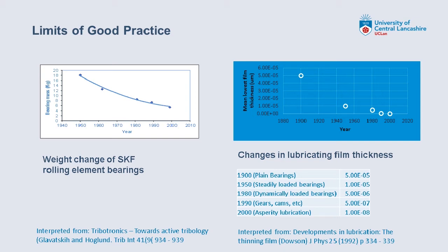If we look at the curve on the right, this curve illustrates typical operating film thicknesses since 1900. And you can see here that in 1900, operating film thicknesses were of the order of 50 micrometers, typically in journal bearings, for example. And that has decreased as the decades have gone by. I've taken some data from a paper by Duncan Dowson here called the thinning film. And you can see now that as we move through the decades since 2000, films can be extremely thin, so certainly a few nanometers in some applications through a process of asperity lubrication.